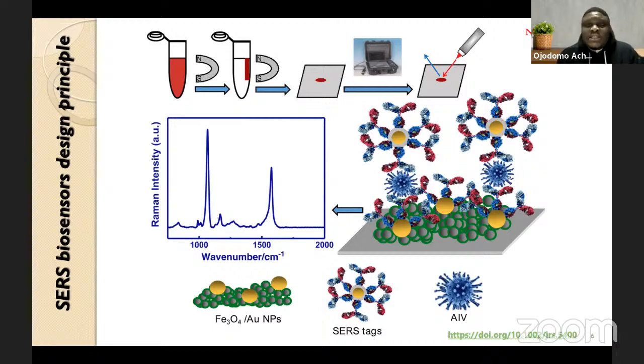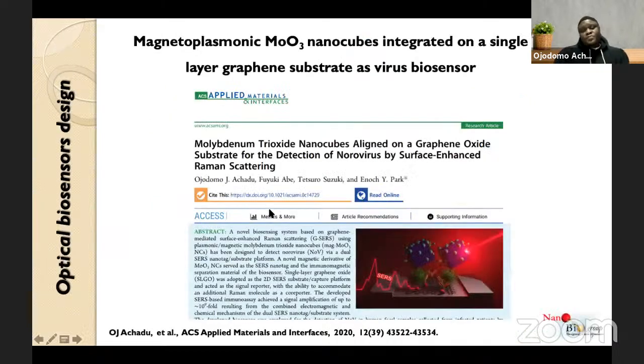So we actually have used this same principle to fabricate a nanosensor for norovirus detection using the 2D graphene material as substrate. So instead of using a blank or bare glass substrate, we fabricated a graphene substrate, due to the fact that graphene also has some contribution to Raman enhancement. So using molybdenum nanocubes, we were able to synthesize novel materials, making use of the novel plasmonic property of molybdenum in the cubic nanostructure, which can generate more intense Raman scattering based on edge effects.